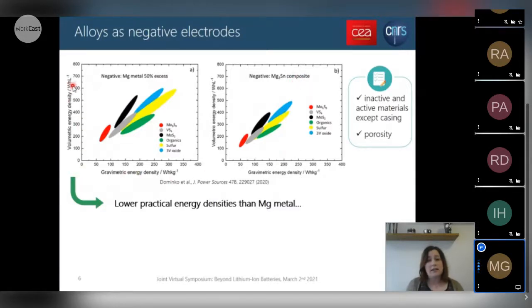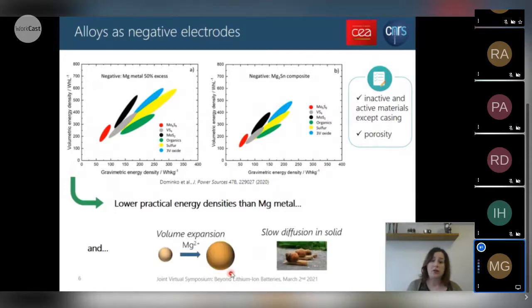So here are displayed the volumetric energy density as a function of gravimetric energy density for different cathode materials with this magnesium metal and this Mg2Sn electrode. As you can see, and as we can expect with these alloy materials, we get lower practical energy densities than magnesium metal. And with these alloys, we also have two other challenges, which are, similarly to lithium batteries and materials such as silicon or tin, a quite huge volume expansion upon reaction with magnesium.